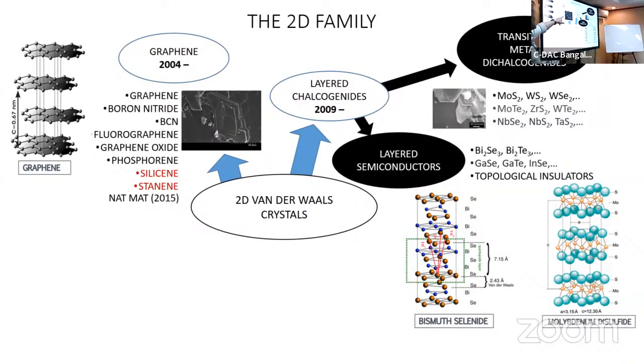Whereas we have the transition metal dichalcogenides, like molybdenum disulfide, which are semiconductors, and they are amazing semiconductors. They have a direct band gap, unlike silicon, which is indirect. But they also have extremely strong light-matter interaction. If you take one molecular layer of molybdenum disulfide, you can take 5% of the light and convert it into electricity. It is much larger than bulk systems like silicon or germanium. So that's why we were interested in this.